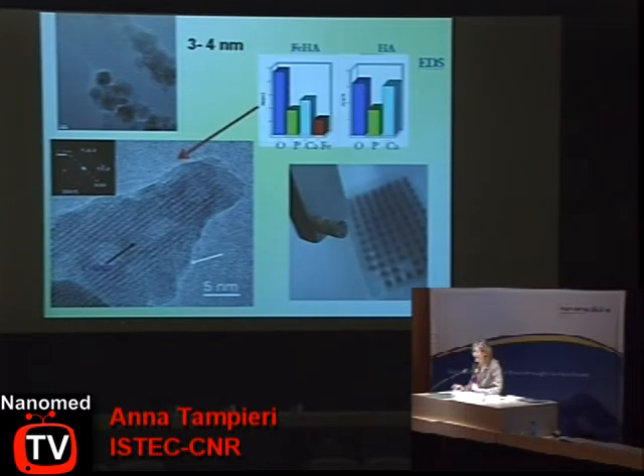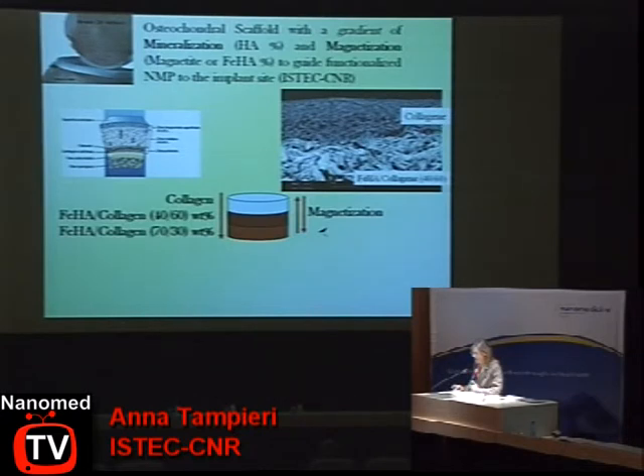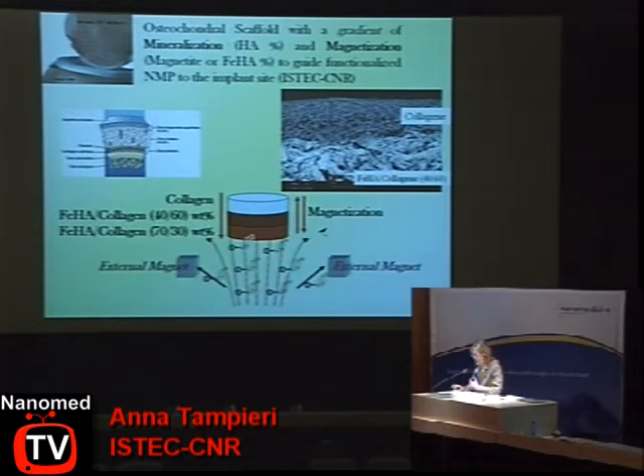And the two iron species were introduced in a specific coordination so that we have a magnetization at a very low external magnetic field, at very low. It's around 1 emu per gram, which is very good. This is the biohybrid composite. We nucleated these phases on the collagen, and so we are able to prepare a superparamagnetic osteochondral scaffold with a graded distribution of iron ions. So the scaffold can have a magnetic gradient and can attract vascular or remodeling bone growth factors inside the scaffold itself.